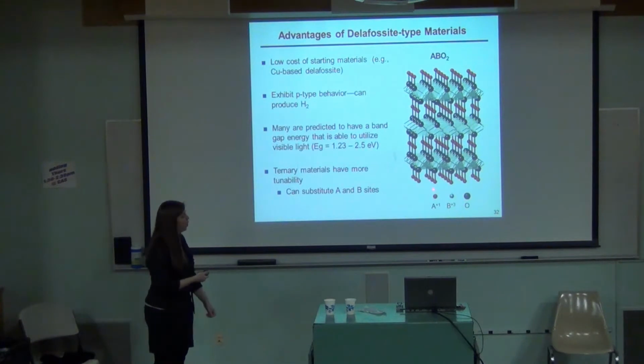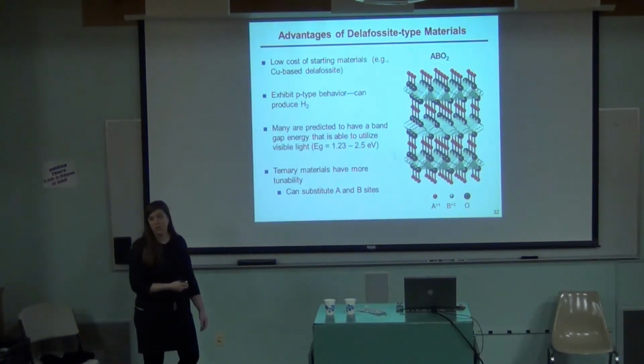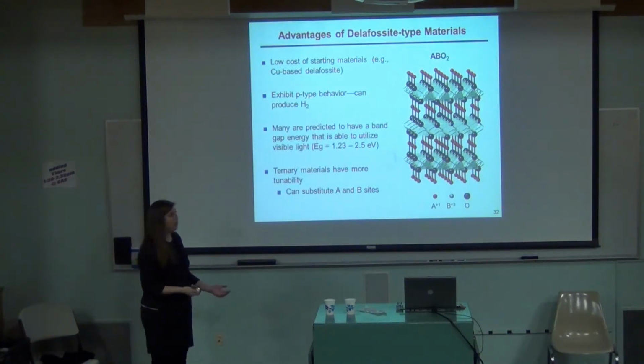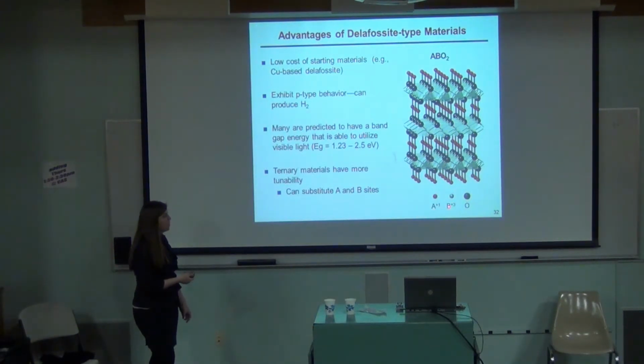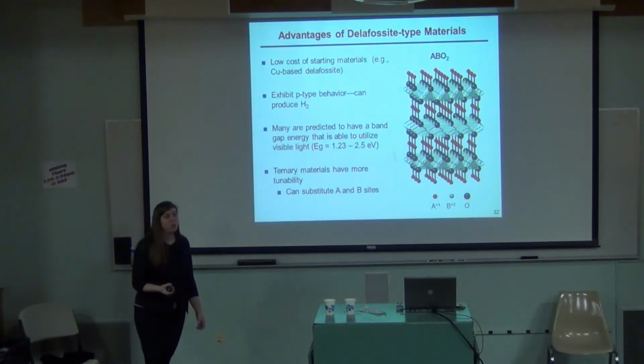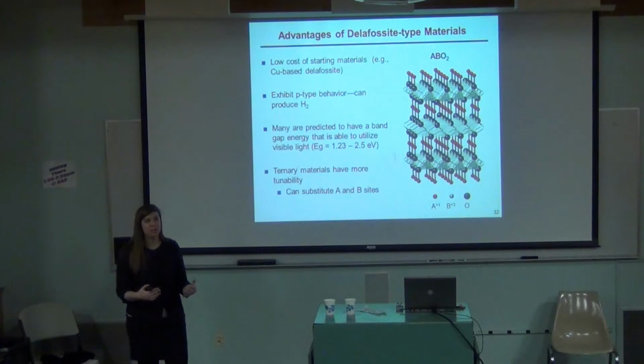Or you can have anything that you want in these sites. So the only criteria is that you need to get something in the A site, which is all of these red spheres. It has to be a 1+. In the B, it has to be a 3+. So that's the only thing you have to worry about. So you can have silver here, or you could have copper here, or manganese, you can have iron, you can have cobalt, you can have anything you want in those sites as long as they can be in that oxidation state.